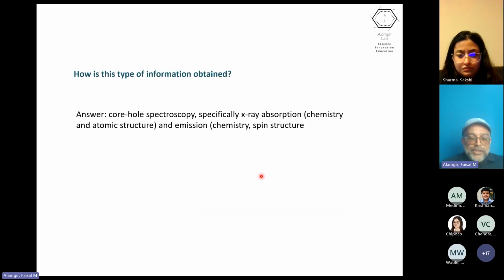All right, so how is this type of information obtained? So I kind of gave it away earlier, but the way you can get at a lot of this information is by triggering the specific atoms that you're interested in to give you that information. And so the way to trigger the specific types of atoms is to basically knock out their core electrons and then use that core electron being knocked out directly, which would give you something like photoemission spectroscopy, XPS, or look at the process by which the photon had to be absorbed in order for that electron to be pushed out. That's the X-ray absorption spectroscopy.